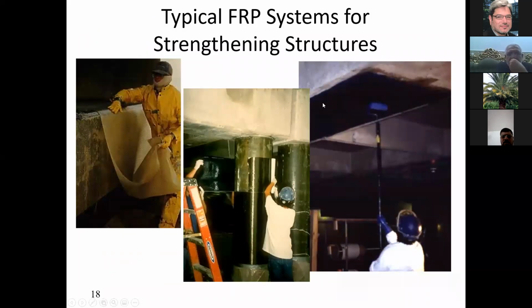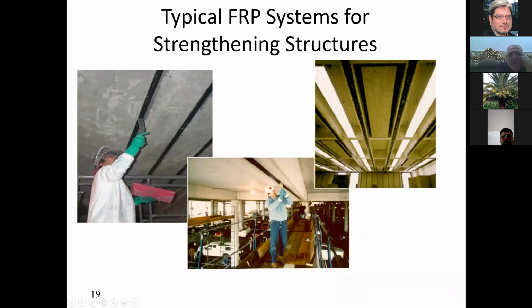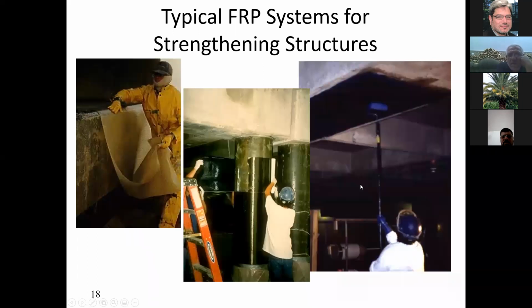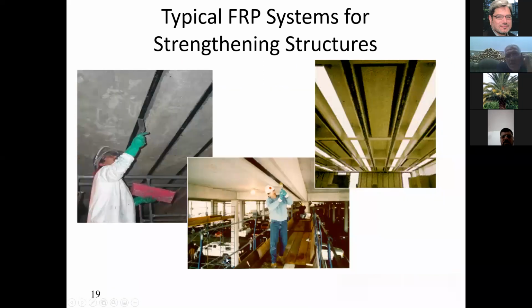So you can see here typical FRP strengthening systems. For example, this is column wrapping for confinement of concrete in the columns, to increase the strength of the concrete inside the column. This is glass fiber being used for shear strengthening, and this is carbon fiber being used for strengthening in flexure. The previous slide showed you what's known as fabric, which can conform to any surface. These ones are strips, and they are used for flat surfaces.